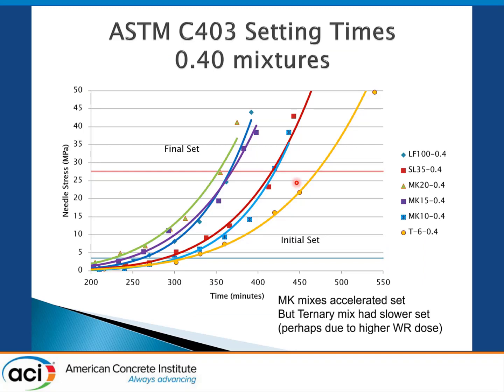We measured setting times. The Portland cement is the blue diamonds here. The slag was pretty much the same in terms of setting time, initial and final set, as the Portland cement, but the metakaolin mixes were faster by about half an hour or so. The ternary blend of slag and metakaolin, on the other hand, had a slower setting time, but that may have been due to the higher dose of polycarboxylate, which may have delayed the set there.